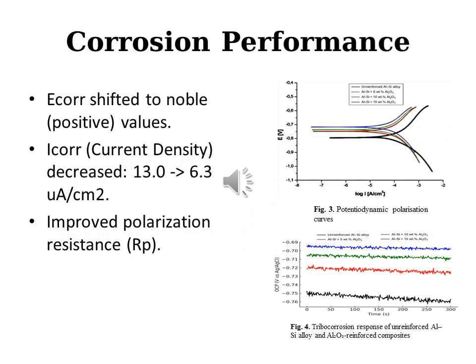In slide 7, corrosion performance. In terms of corrosion performance shown in Figure 3, the polarization curve shifted to more noble positive voltage with the reinforcement. The current density decreased significantly from 13 down to 6.3 microamps per square centimeter, indicating improved polarization resistance.